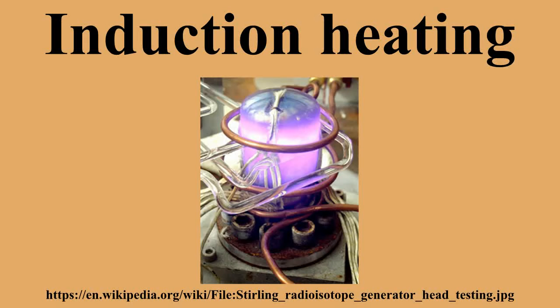Induction furnaces often emit a high-pitched whine or hum when they're running, depending on their operating frequency. Metals melted include iron and steel, copper, aluminium, and precious metals. Because it is a clean and non-contact process, it can be used in a vacuum or inert atmosphere. Vacuum furnaces make use of induction heating for the production of specialty steels and other alloys that would oxidize if heated in the presence of air.